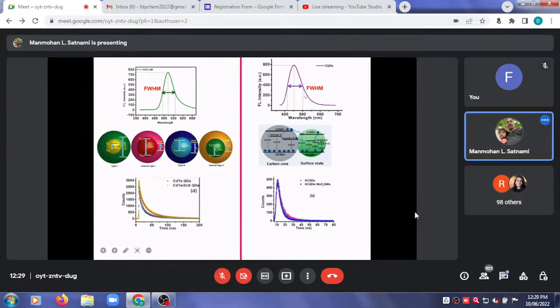Full width half maximum. So if there is any organic molecule, it absorbs energy and it gives you absorption spectra. The absorption spectra can be very broad and can also be very sharp, okay. So for any quantum dot or any emitting nanomaterial, their full width half maximum should be minimum, and if it is around 90 nanometer then it is very good. So both the semiconductor quantum dot and carbon quantum dot give the full width half maximum at around 90 nanometer.